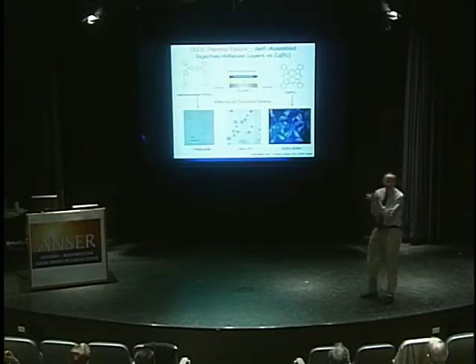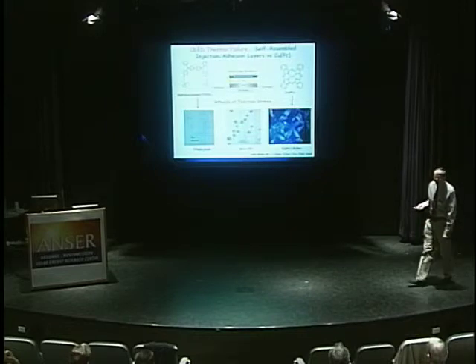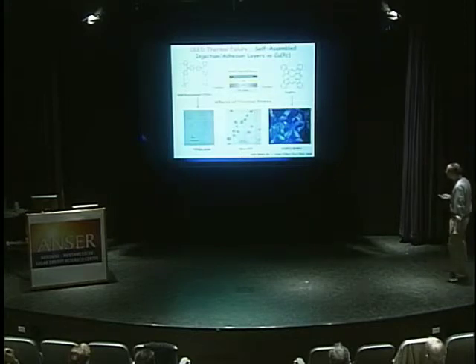Why? There's a terrible surface energy mismatch. You put something very hydrophobic on something very hydrophilic. And in fact, this was the problem with the first generation of Motorola OLED phones, which you can only buy now on eBay because they were all pulled off the market. And it had to do with the fragility of this interface. So Kodak attacked that by using copper phthalocyanine and other kinds of interlayers. They don't really work terribly well either.